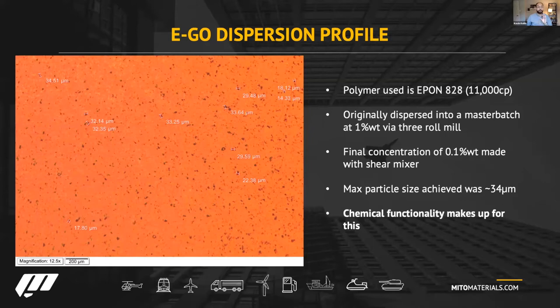So the optical image that you're seeing here is within EPON 828, which is 11,000 centipoise. We originally dispersed into a master batch with a 3-roll mill at 1% and then let that down to 0.1% with a shear mixer. The largest particle size is about 34 microns, but the chemical functionality makes up for that to where we get some large increases.